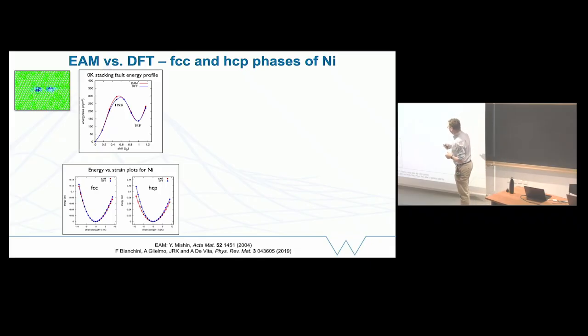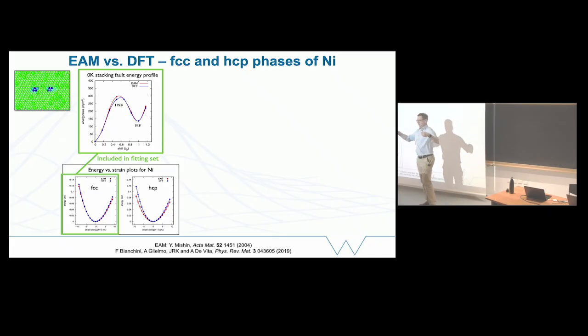This is quite challenging. We have to think about what we put into the potential and what we get out. I'm trying to use this as a general example of when you fit potentials, it really matters what you put in your training set, what you think you need to get right. So in this case, this is an FCC material, so we put in the FCC energy volume curve. We carefully make sure we get the energy right as we stretch the FCC material.